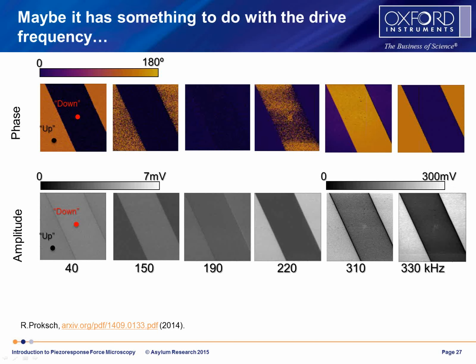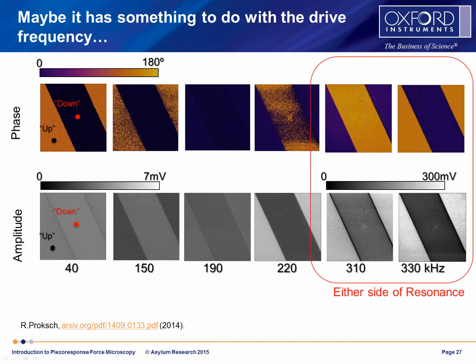The first thing I thought about is maybe it has something to do with the frequency. This is a very common thing in the PFM literature, that there are different sensitivities and different effects at different frequencies. So here is a series of images, six images of the phase on the top and amplitude on the bottom of three domains in this PPLN sample, all taken with the same identical AC240 cantilever at different frequencies: 40 kilohertz, 150, 190, 220, 310, and 330. The top two are on either side of the contact resonance. You can see the signal to noise is really spectacular there. However, the amplitude is very different on the two domains, unlike what we would expect. Also, the data scales below resonance and at resonance are quite different.